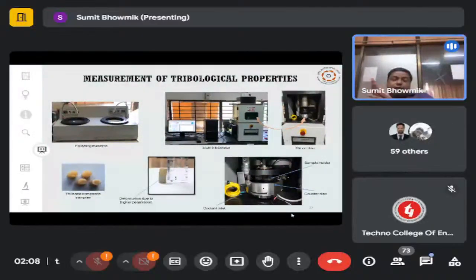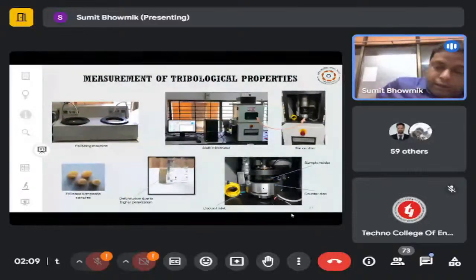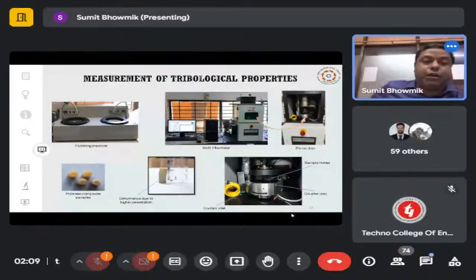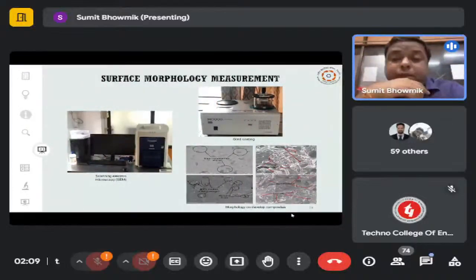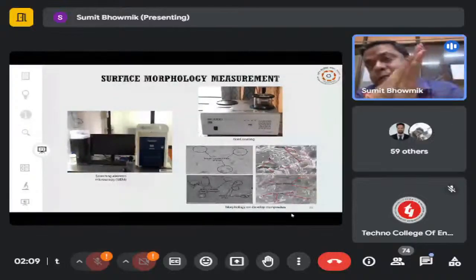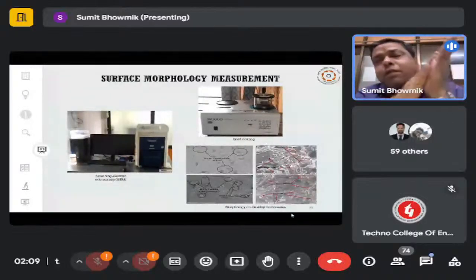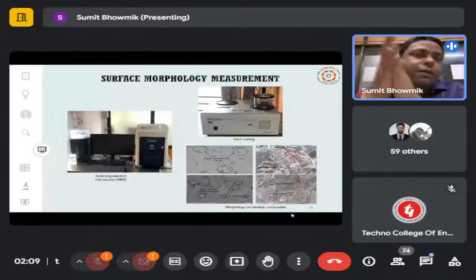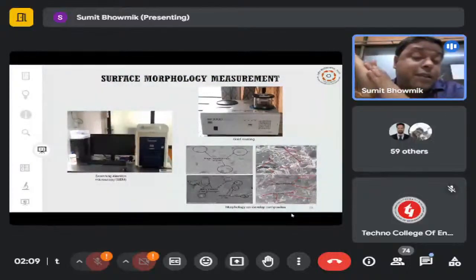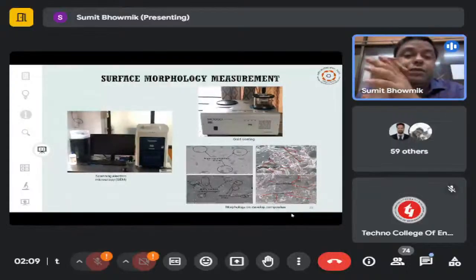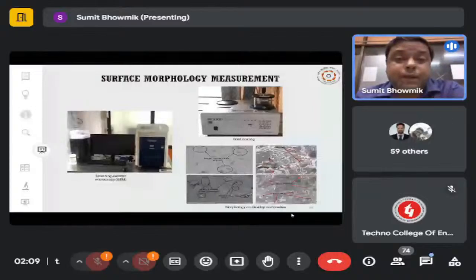In most cases we have considered cylindrical samples, and when we bring the sample out from the mold, there is some variation in the dimensions, so it has to be polished properly in a double disc polishing machine, so that the surface is smooth and proper properties can be measured. This is the schematic representation of the same analysis or structure considered. In most cases it has been observed that the thermosetting polymer composite developed here is non-conductive to electrical and magnetic properties. So sometimes it is very difficult to examine even the fractured surface without some coating, so a gold coating has to be done, and then the same analysis is carried out.